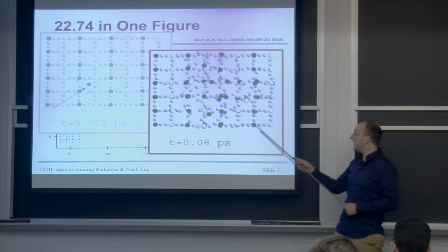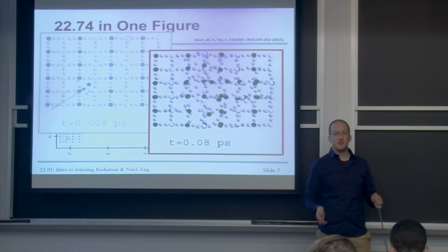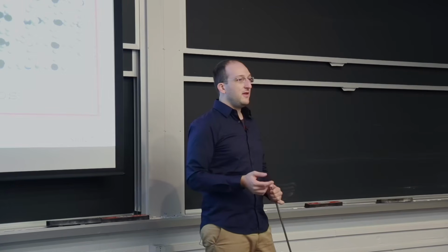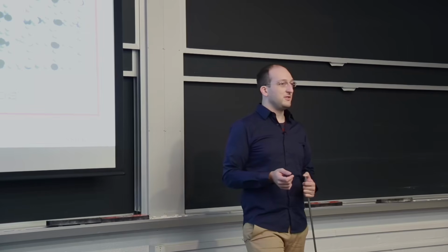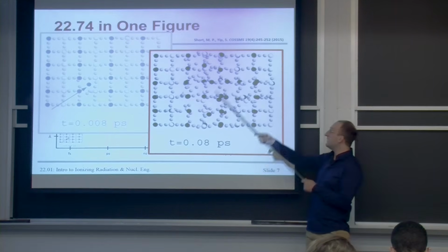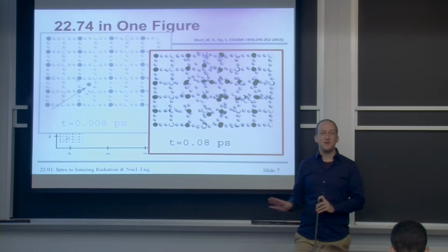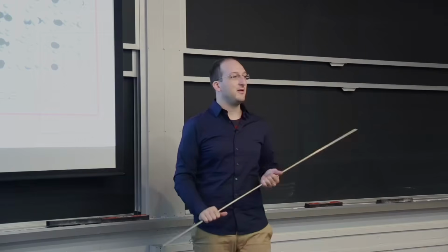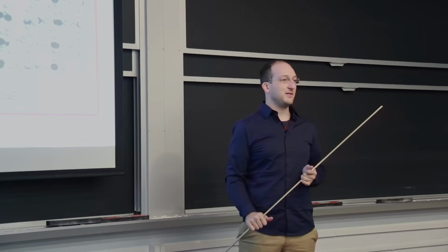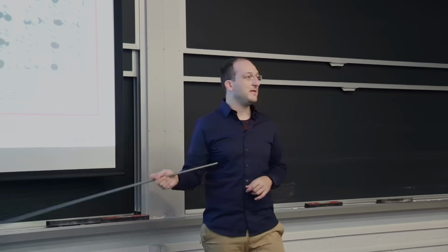If you think about all these atoms, they're vibrating at fractions of an eV, at thermal energies, like the thermal neutrons we talked about in the reactor. Then you hit them with an MeV neutron, they might transfer 100 keV of energy. And a bunch of these atoms will then be moving about at, let's say, a few hundred eV. That's way beyond liquid temperature. So actually, it's been theorized that there's a little pocket of atoms around 3 to 5 nanometers wide that reaches like 10,000 Kelvin for a very, very short amount of time, less than a picosecond.